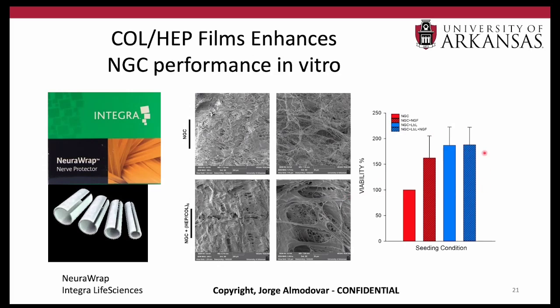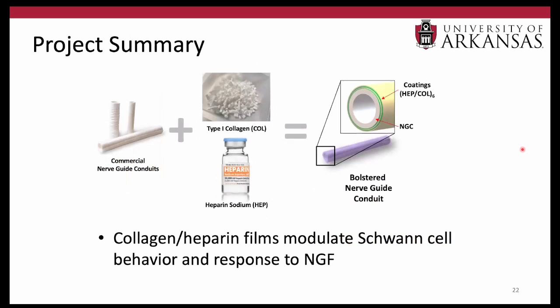But then when we culture Schwann cells on the scaffold with and without the coatings, we see some very interesting results. Again, measuring just the viability. In the blue here are conditions with our coatings, and we can see that cells are more viable with the coatings, regardless of whether we have NGF or not. So again, a very favorable result as well. This is a project that we're continuing to explore with different avenues, but overall we're seeing that these coatings really do improve that cell behavior, that Schwann cell behavior.